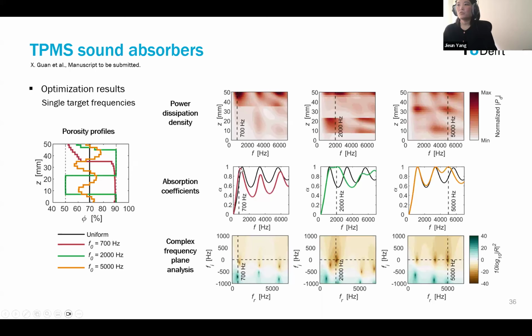So we could see that to increase the sound absorption coefficient at this 700 Hz, the optimization profile was trying to shift this absorption peak by allocating these layers with lower porosities on the top, which is kind of similar to micro-perforated panels. And then if I jump to this third case first, it has this gradually changing sine wave like profile. And then you see that when they have these lower porosities, they have slightly increased dissipation. And by modulating this porosity, they also change the tortuosity inside the whole porous layer. So they can actually shift this peak to the lower frequency.